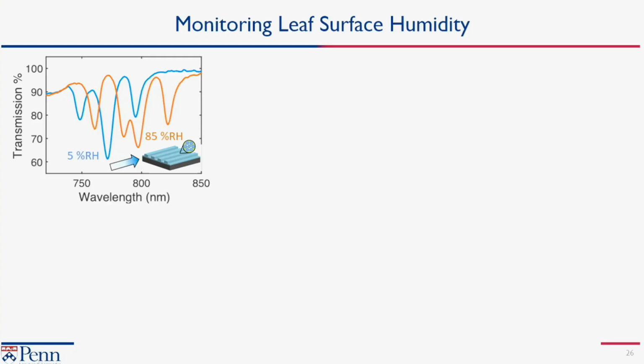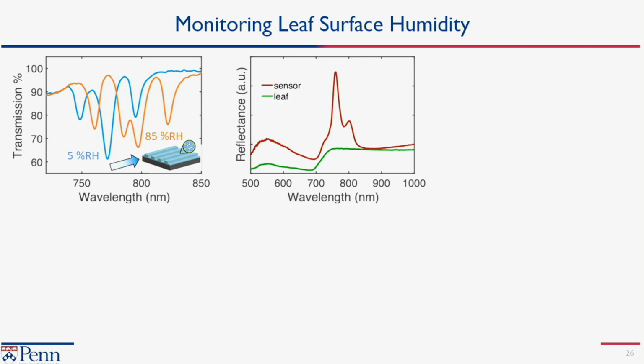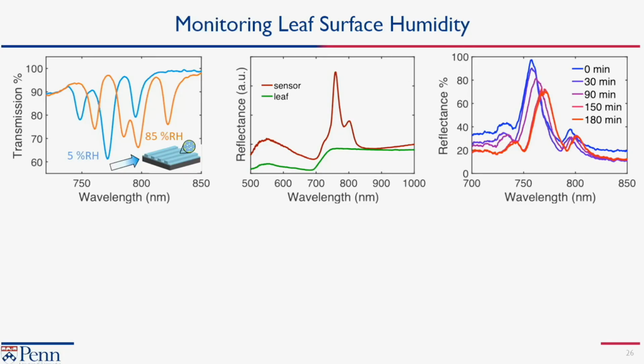So I'll just tell you this last story. Here's an example. If you put one of these sensors at 5% relative humidity, and then you put it at 85% relative humidity, you can see the shifts in the spectra as you go. This is the reflectance of the sensor. This is what the reflectance of a leaf looks like. And so you can really pick out the sensor from the leaf. And what we did is we put the sensor on the leaf and let it equilibrate. As it equilibrates on the leaf, you see it shift. And that's because when you put it on the leaf, the moisture from the leaf actually creates a very high humidity state that the sensor sees. So now we have to put this on the leaf.